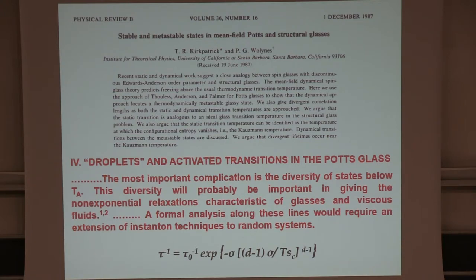So what was going on here? Well, of course, again, knowing the answer, that's the great thing about physics. We know it, we have the back of the book, actual experiments. We know that the experiments tell us there's an actual problem with entropy, and that the temperature at which things seem to slow down forever was related to the vanishing of entropy. And in this model, one could go ahead and calculate the entropy from the Thouless-Anderson-Palmer solutions of the Potts glass and find that actually this transition occurred through an entropy crisis, just like Kauzmann suggested might portend in real systems. Well, also, I wanted to calculate rates.